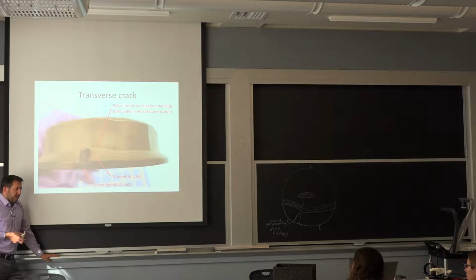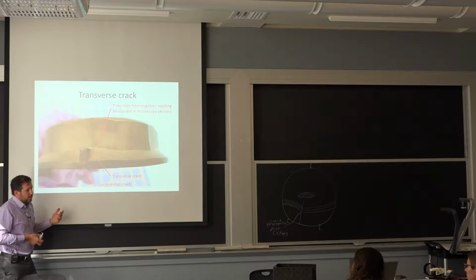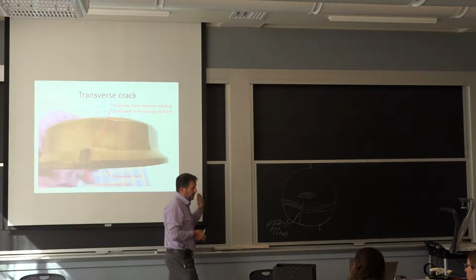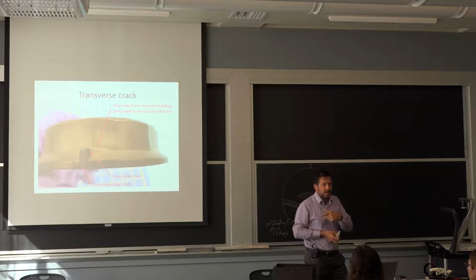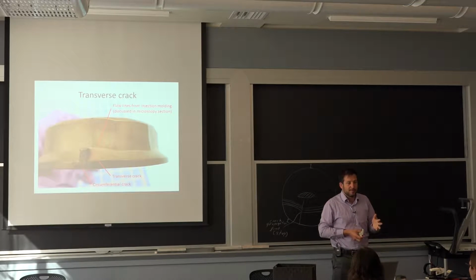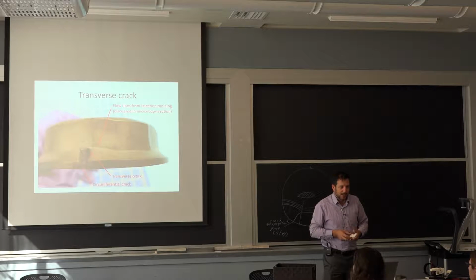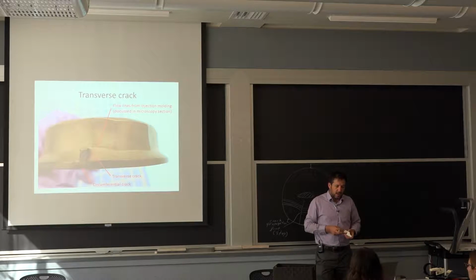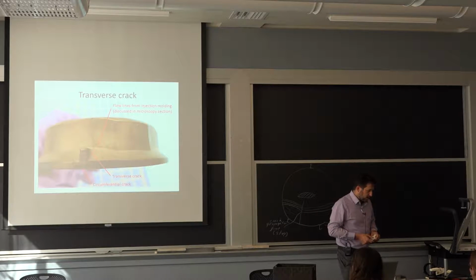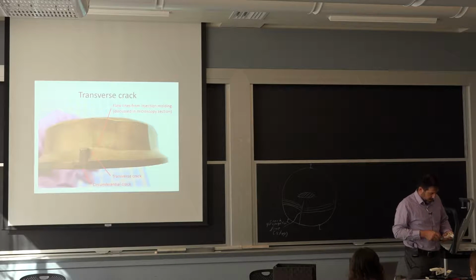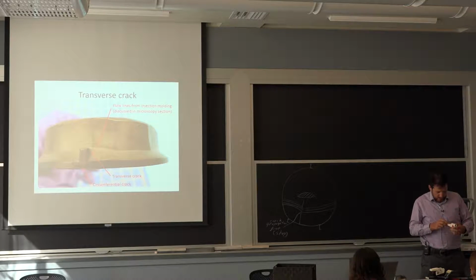So I think it gives you a little bit of an emphasis that for long term, I mean, this nut essentially failed after 5 years. Nobody touched it, apparently anyway. And it essentially is a sort of a creep process that happened, so you don't see it right away, and it's associated with just very, very small changes on the surface. So it's a little unfortunate, like a lot of other parts, and they make a lot of efforts in the injection molding process to try to avoid all these mold lines, of course, but it's very difficult.